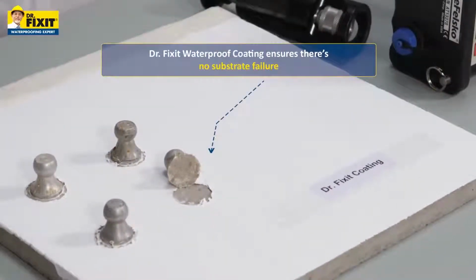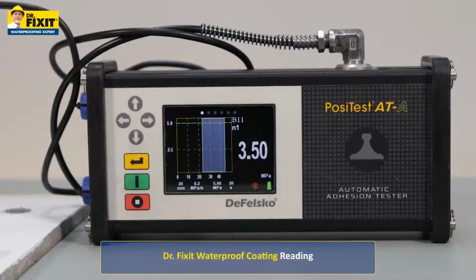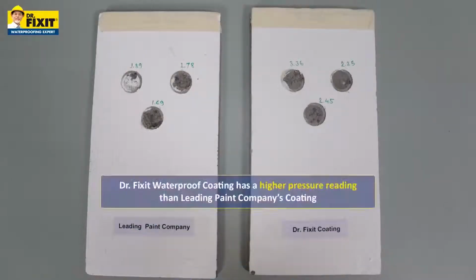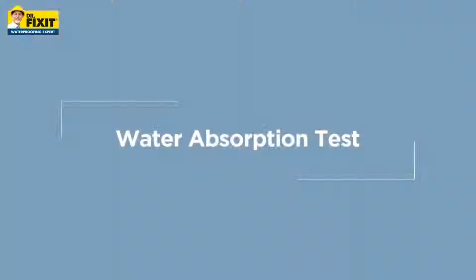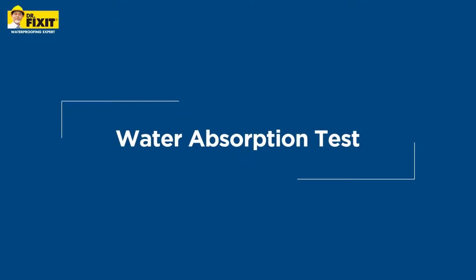Dr. Fixit Raincoat waterproof coating has excellent adhesion to concrete and masonry walls. Results indicate that Dr. Fixit waterproof coating has a stronger adhesion to the substrate as compared to the leading paint company. This test shows the water resistance of the film. Good exterior paints have a lower water absorption rate, which is required for better waterproofing properties.